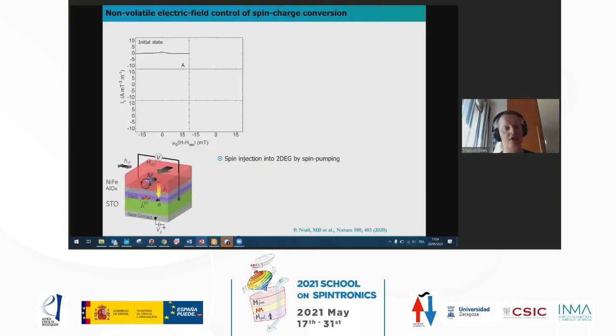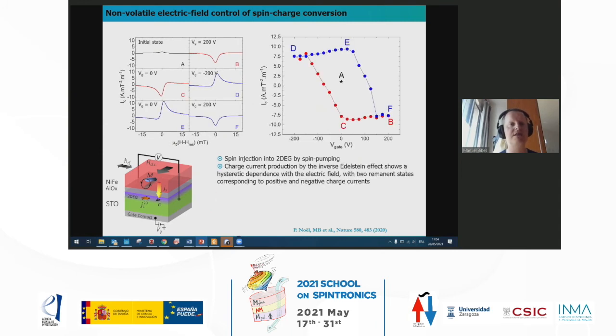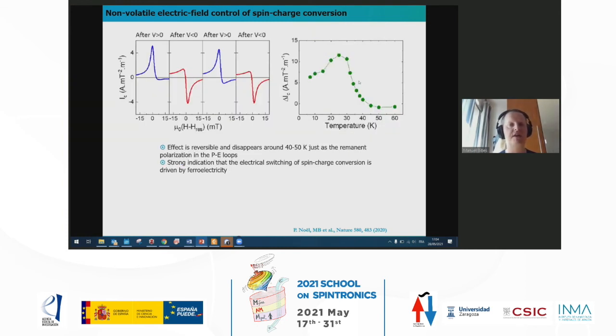And then, of course, we tried to see how this ferroelectric-like state was going to influence spin-to-charge conversion. I'm going fast because I'm running out of time. But basically, we see that we have a hysteretic dependence of the charge current produced in these experiments with the gate. So we have a completely different dependence on the gate than we had before, and we have here 2 remnant states, okay? And the efficiency of the effect also disappears at about 50 K. So this is another indication that it is probably driven by ferroelectricity.